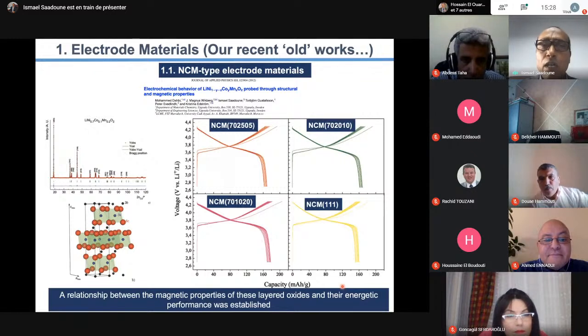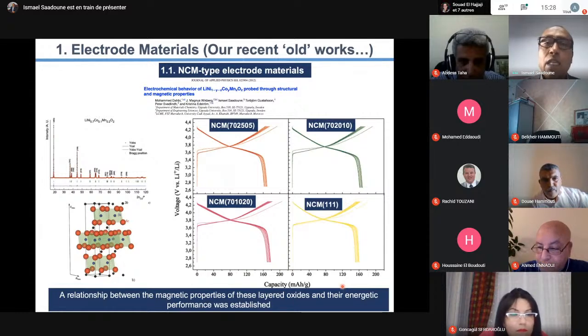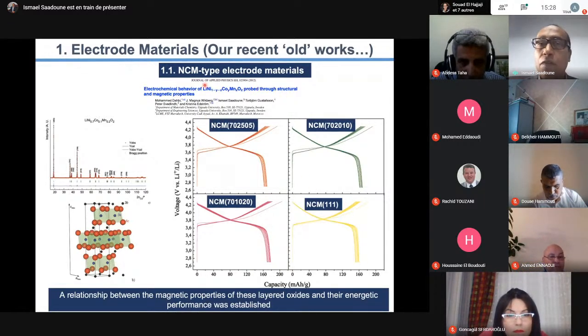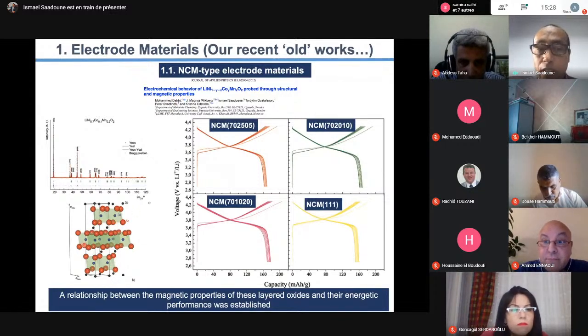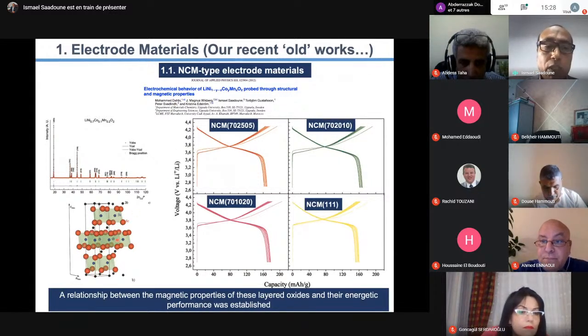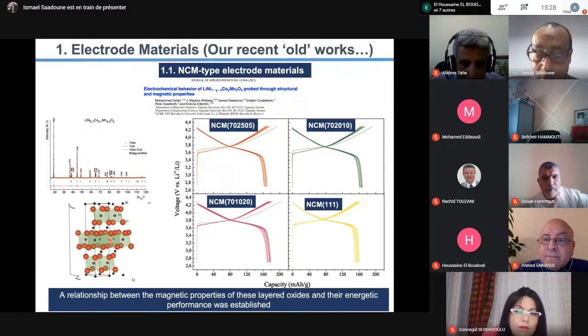Our other approach, for university R&D, is to correlate the electrochemical performance of this NMC material to their magnetic properties. In the structure, you have a layered structure with transition metals in the slabs - nickel, cobalt, and manganese. Cobalt is diamagnetic, and nickel and manganese are paramagnetic.